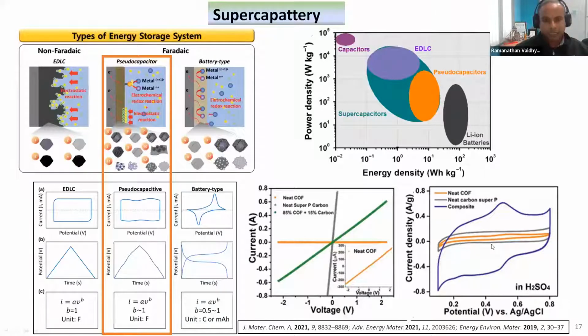But what is the problem with this? As I told you, a pseudo capacitor works on the principle of charge being stored in it, which means your COF is going to act like a sponge, which really absorbs all the ions under your applied potential. But for that sponge to work very well, two things. If you have electronic activity, it will work very well because it can really get charged negatively, which means it can attract a lot of oppositely charged ions into it. But at the same time, this carbon that we add is a dead material. This has only electronic conductivity and no sponge-like behavior. So you ideally want to avoid this carbon, which is a dead material, which adds no sponge-like behavior, and make a single material which is spongy as well as electronically active.